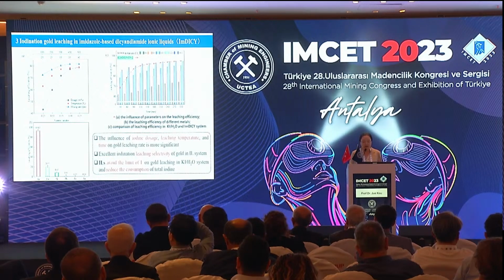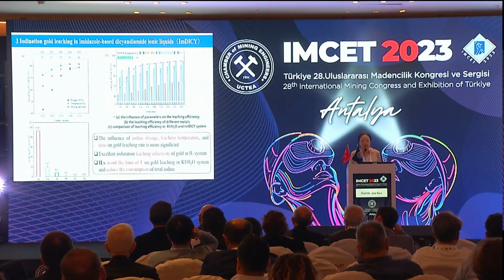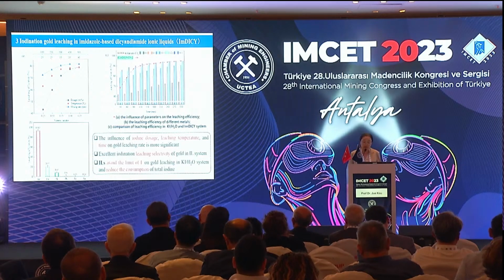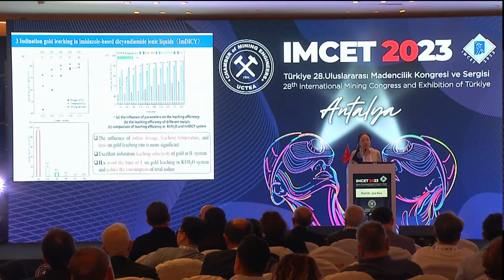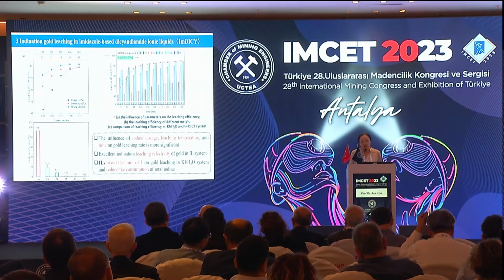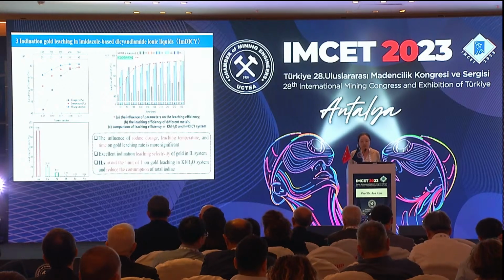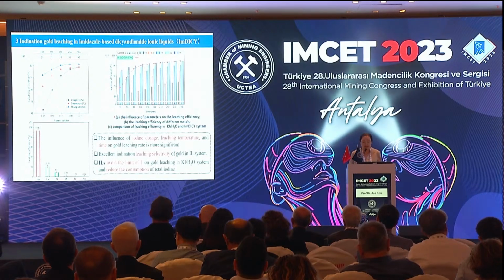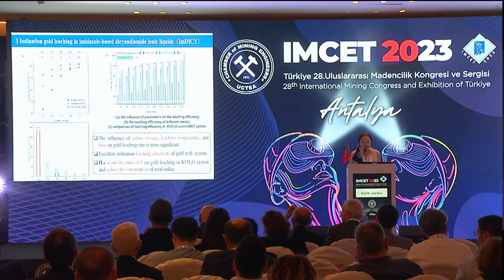Okay, this figure is a comparison of the water solvent iodine gold leaching and the ionic liquid solvent leaching. To get the same leaching rate, above 90%, in the water solution, the potassium iodide concentration is 10 times that of the iodine. But for the ionic liquid, no potassium iodide is needed in this process. The influence of iodine dosage, leaching temperature, and time are all shown in this figure.